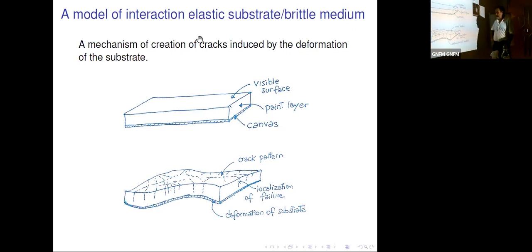So what you expect is that as you deform the substrate, this is a mechanism driven by the deformation of the substrate. As you deform the substrate, the deformation expands to the layer, which is brittle, so it may crack, it may dissipate elastic energy. And what you see then is that you localize, so instead of having everywhere a diffuse elastic response, you have a localization of the displacement, of failure, in some directions, in some zones, and then what you see on the upper surface is an array, a pattern of cracks.